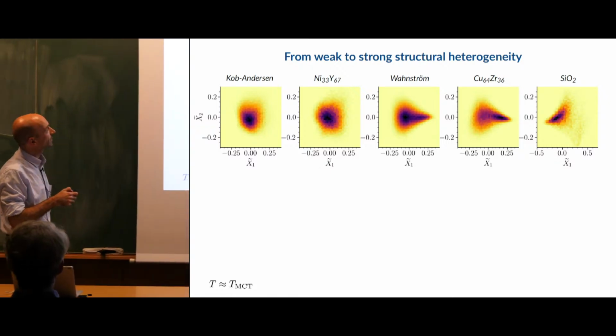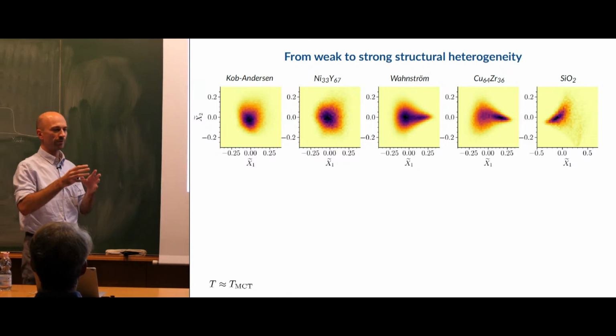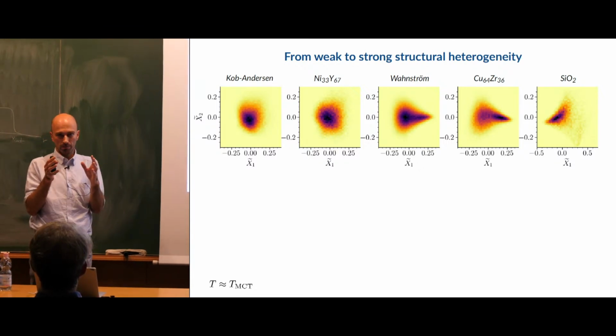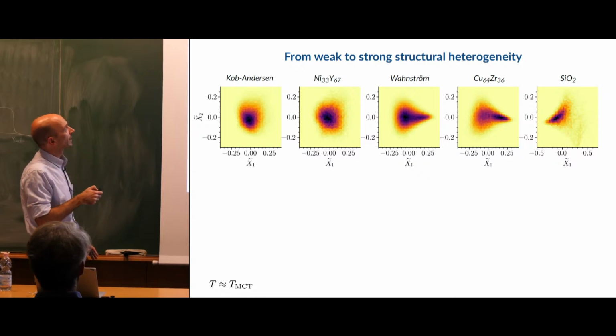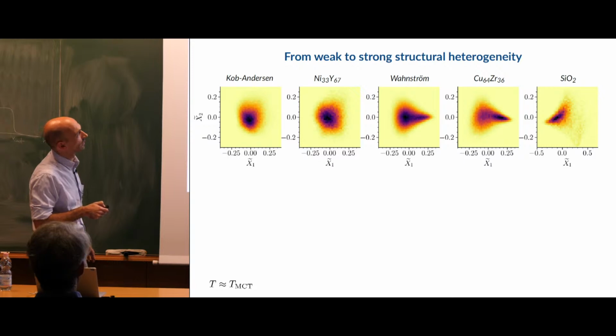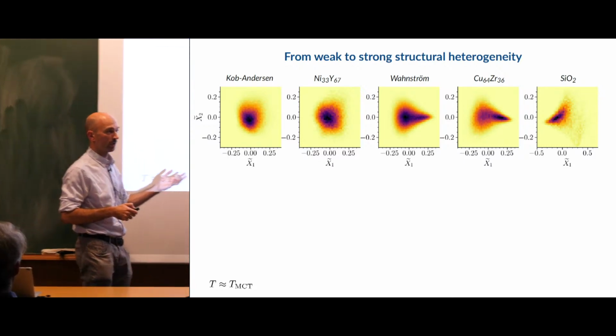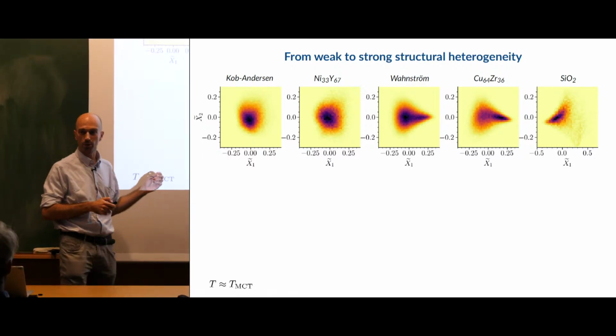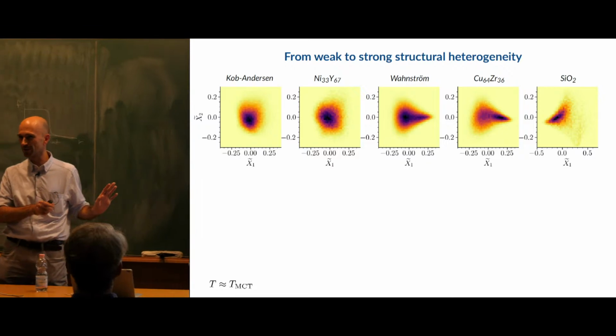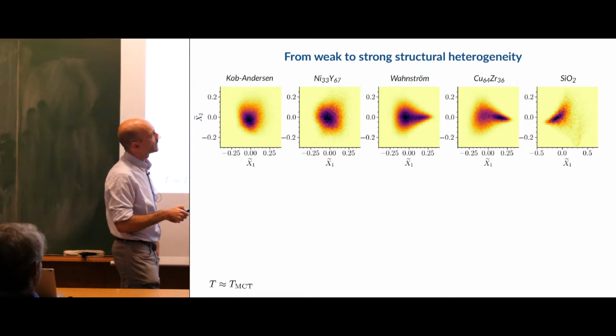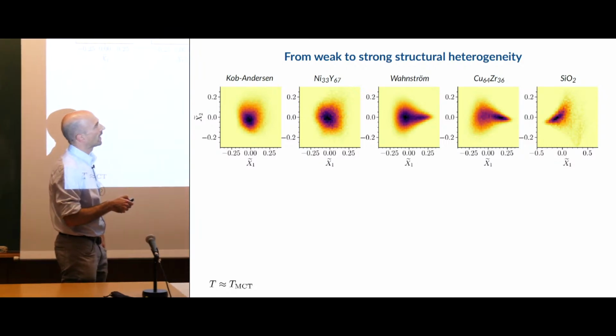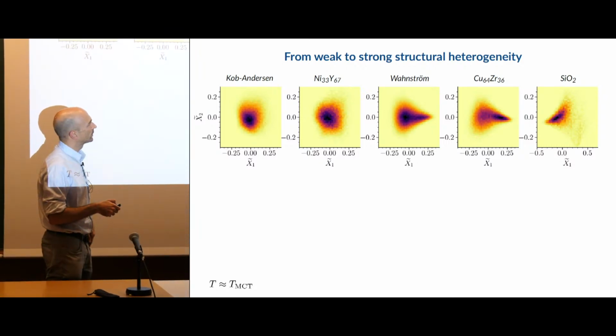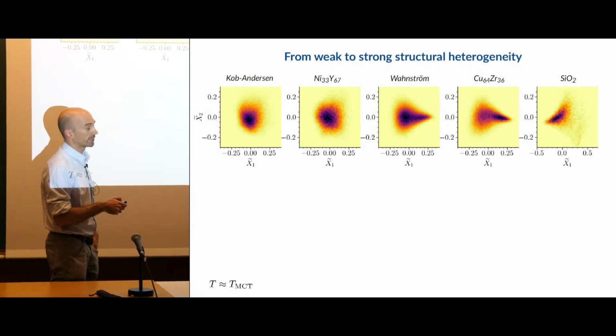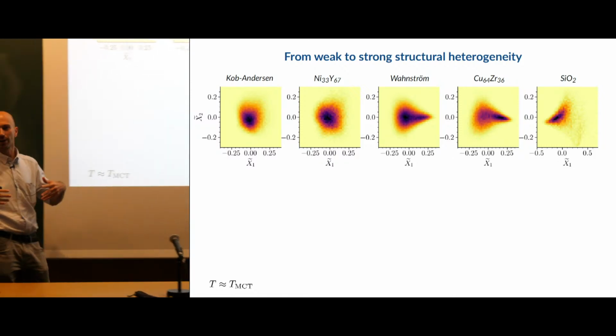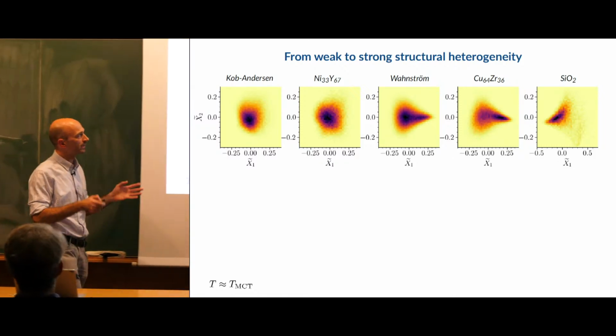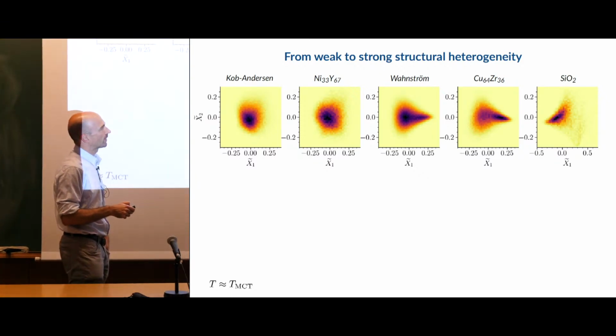So what I see here is that in these 2 models, maybe there's a broad range of reduced features, but the distribution is more or less unimodal. Okay, so there's a single blob, a central spot, whereas in these other two, there's an additional lobe, and this is due to icosahedral order. And this is actually the same also for this copper zirconium mixture. So basically the same phenomenology as the Lennard-Jones mixture. And in the amorphous silica, you get a range here that corresponds to ideal tetrahedral environments, and then a diffuse area. I'm not sure if you can see, but there are many spots here corresponding to defects in the structure, like under-coordinated environments. Okay, so you can clearly see that there is one favored local structure and many, many defects.